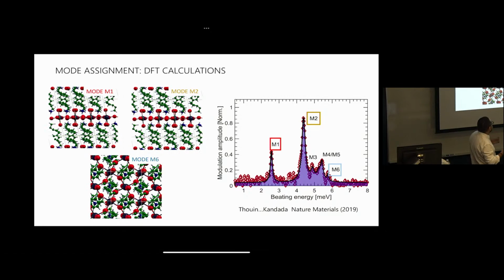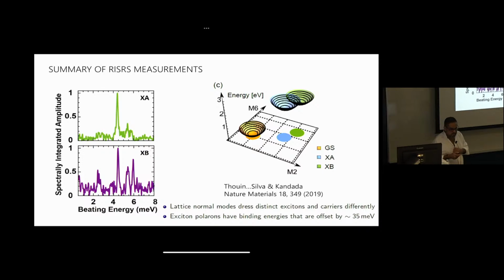And so here we have a Raman spectrum. We know what the phonon modes are, at least by comparison with the ab initio calculations. We can assign it, and we know to what extent these couple to photocarriers, and what else can they tell us? Now we go off and do the experiment, the same experiment.